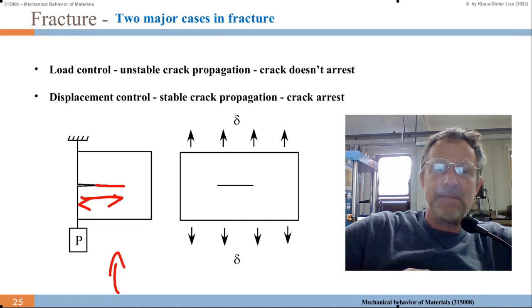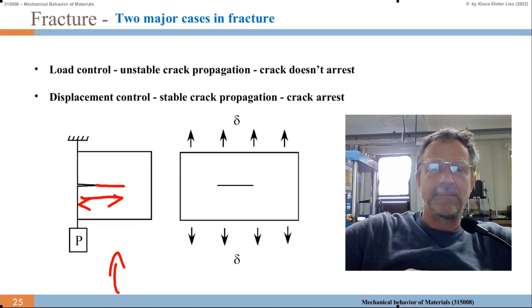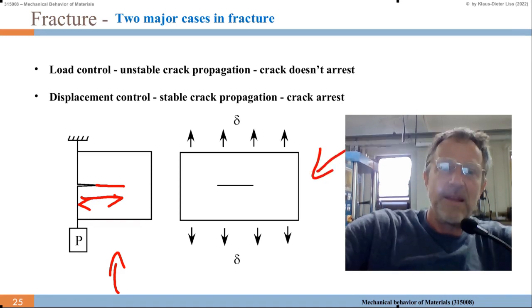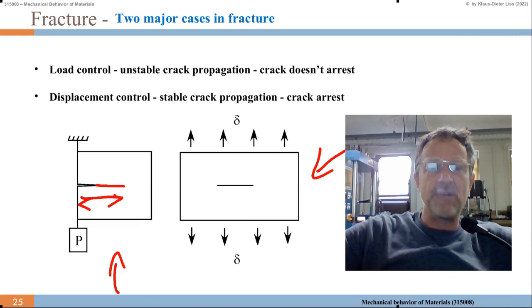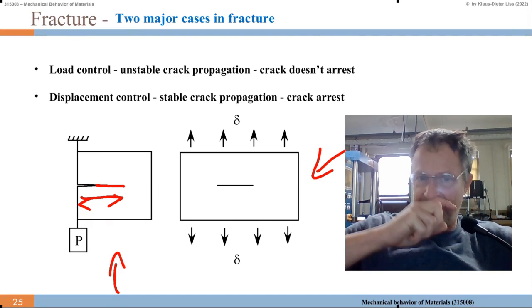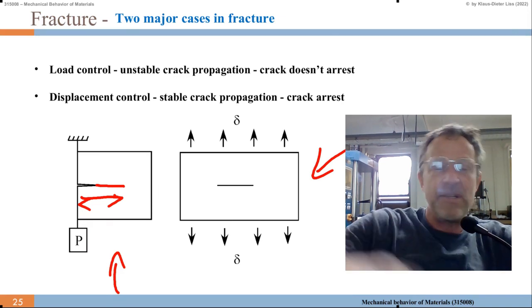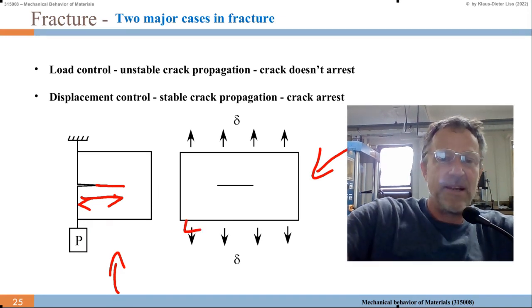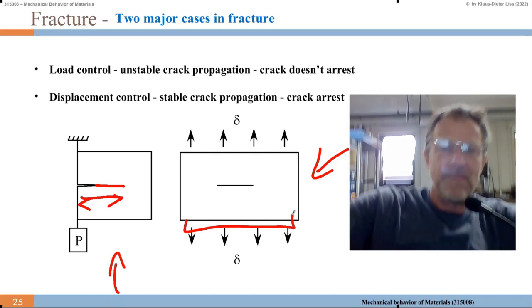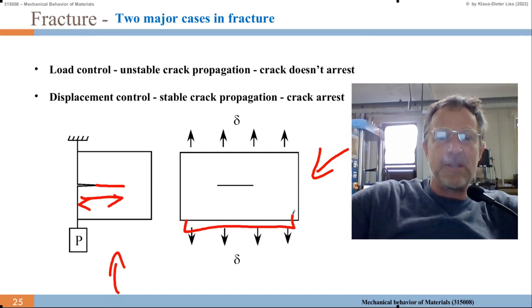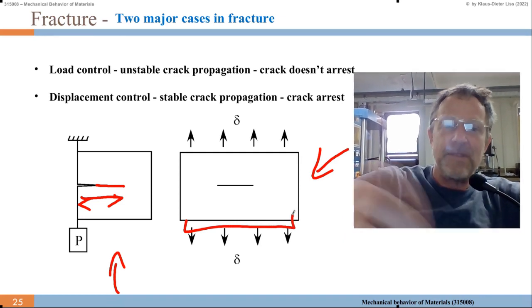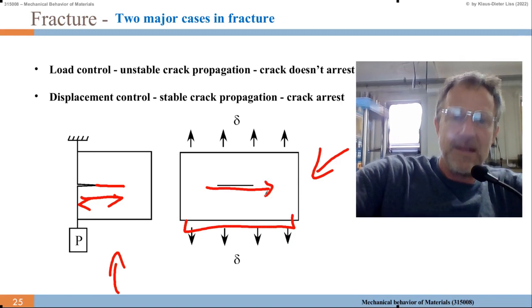Or you have this displacement-controlled situation where we can put it in the middle, for example, just for generality. If we displace and keep the displacement, like with the lever arm now in the center, then it grows to a certain length and it stops growing.